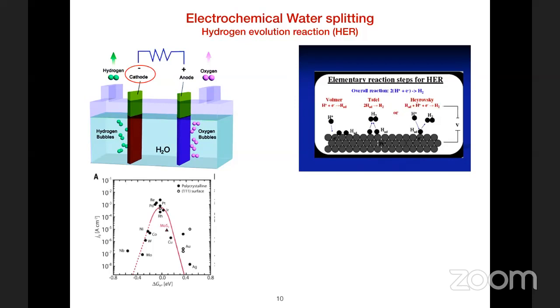The second step could be one of two possibilities. Two adsorbed hydrogens could combine, form H2 and get dissolved, or one incoming H+ can take up an electron and, without getting adsorbed, can combine with a previously adsorbed hydrogen, form H2 and get dissolved. So these are called Volmer, Tafel, and Heyrovsky steps. But the main point is that hydrogen adsorption is essential. And so when one is trying to find theoretically the efficiency of a material for hydrogen evolution reaction, what one looks for is what is the hydrogen